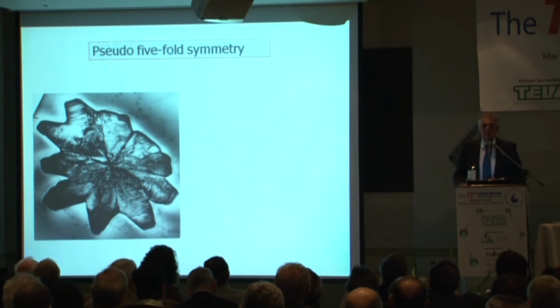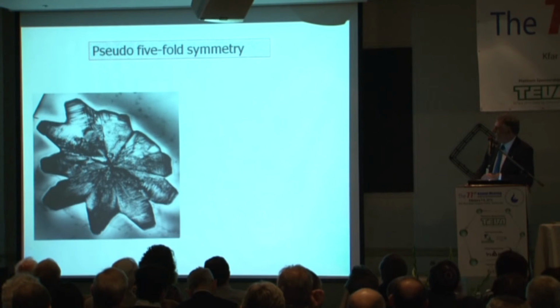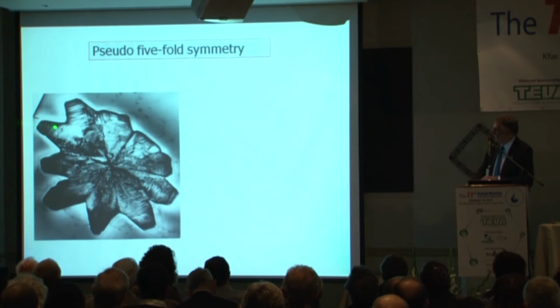This crystal exists in the aluminum-iron system, very abundant, and they are quite large. You can see them in an optical microscope. And I chose this especially little one. What you see here actually are 10 single crystals joined together in such a way that they are twin-related. So this one here is twin-related to this, and this one here is twin-related to this. And in between them, you have a twin boundary. Here is 1, here is 1. These are the twin boundaries.